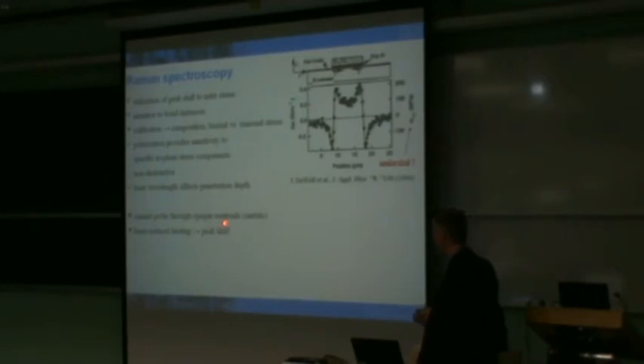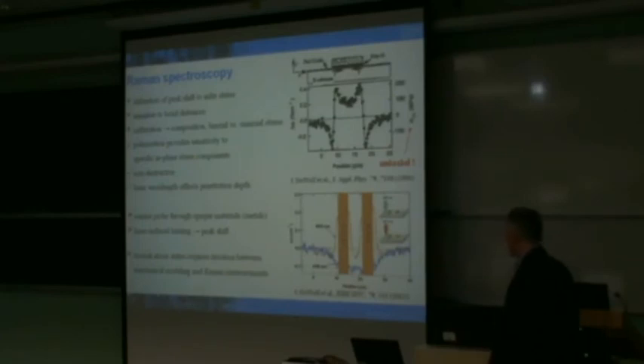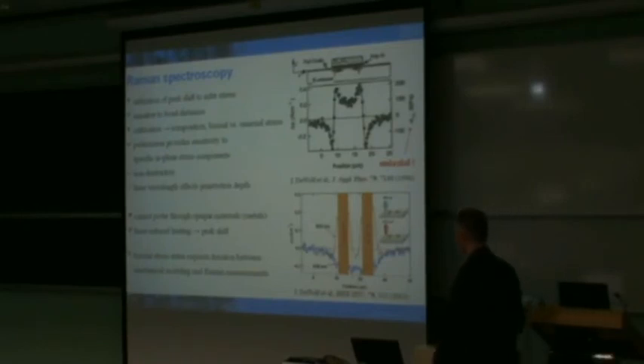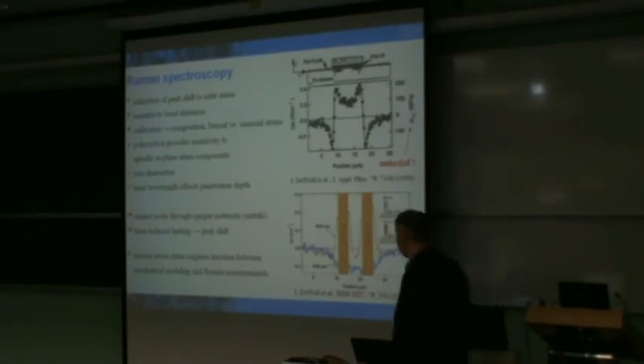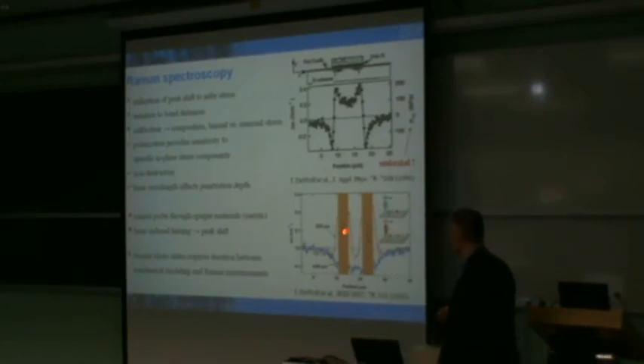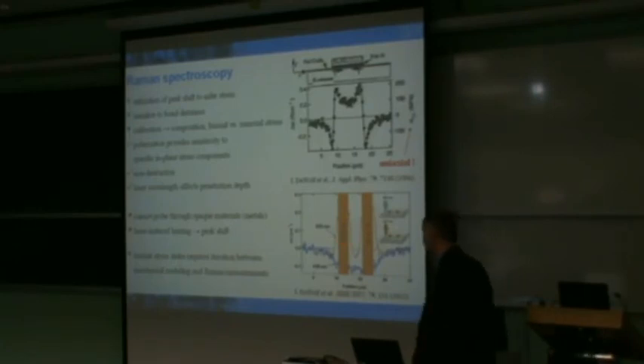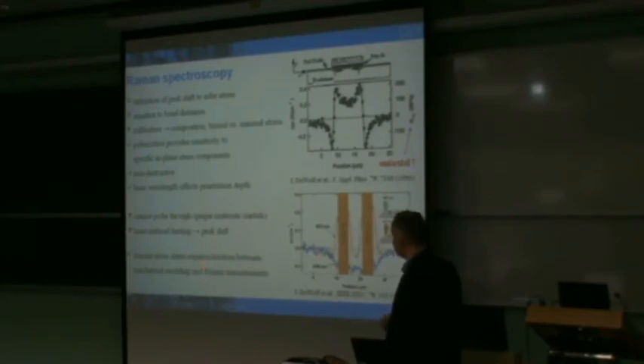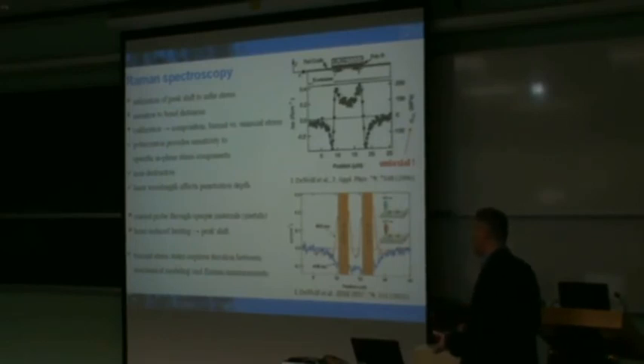One of the main problems is that opaque materials cannot be probed with this technique. And as I mentioned before, you can get artifacts. But still, it is being used to look qualitatively at some effects. One example I'm showing here is that three-dimensional structures and integration involve the incorporation of metallic conductors between semiconductor substrates. That way you can send signals and power between the stacking of different layers and come up with a more computationally efficient volume. In doing so, there will be changes due to this large metallization structure, due to the mismatch in thermal expansion between a metallic structure and the neighboring silicon. To solve this, Raman has been used, but it incorporates a significant iteration between the finite element modeling and the Raman measurements to get a self-consistent answer.